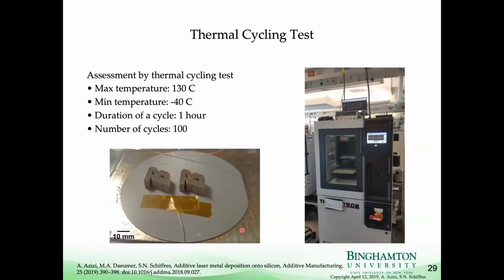We've also done some basic thermal cycling tests. There's still a lot remaining before this could ever be used in practice, but we're still doing more of this. But we did 100 cycles with this Binghamton logo, and it didn't break off. At least we have to do more testing though.